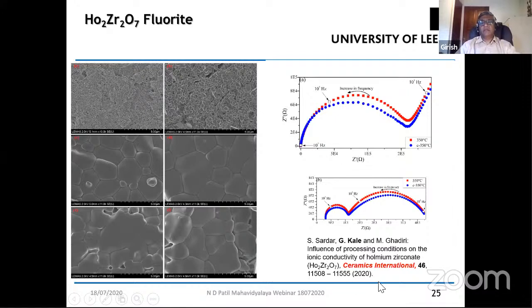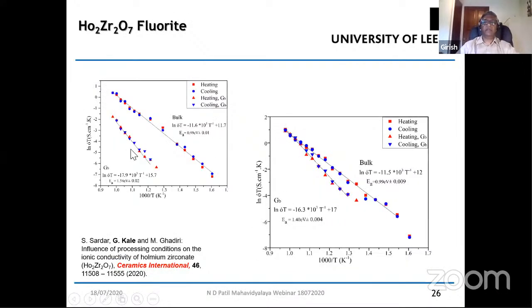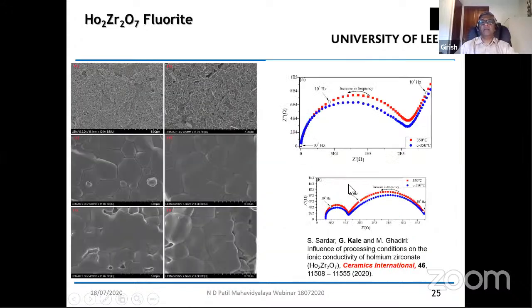Then we did the impedance spectroscopy, the results of which were published recently in Ceramics International. We did impedance spectroscopy to calculate the conductivity, because that is one of the parameters that you need to measure to assess the potential of the material as a solid electrolyte. So what you see here is nothing very unusual. It's basically a standard Arrhenius plot, which gives you the activation energy and the conductivity from the impedance spectra. These impedance spectra are measured over a range of frequency as a function of temperature to arrive at this data.